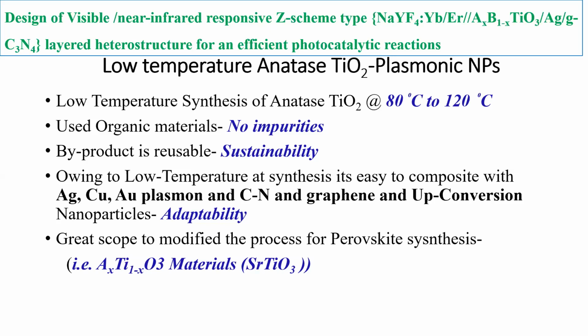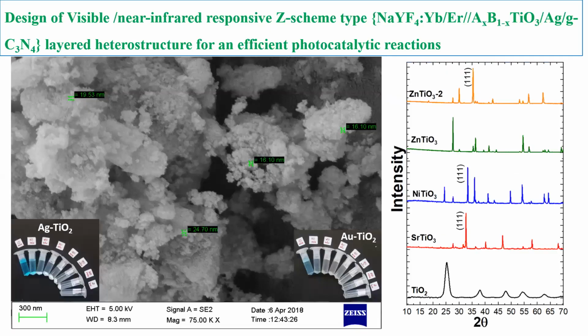Because when we synthesize something and that itself generates a lot of waste, what is the use of making it for the cleaning process? Because my synthesis process itself is generating a lot of waste. So this is something I have made that does not require any electricity. By using sunlight itself, I can make TiO2, and I got very good results. I got approximately 16 nanometer TiO2 only.